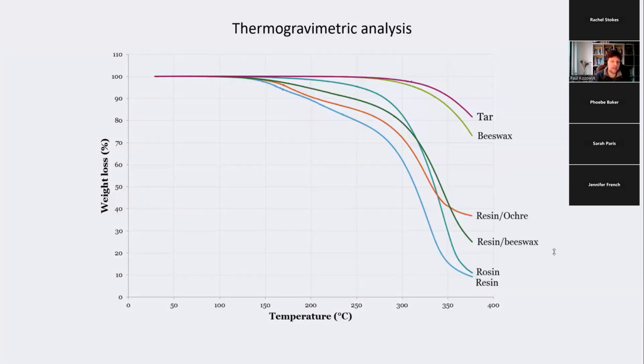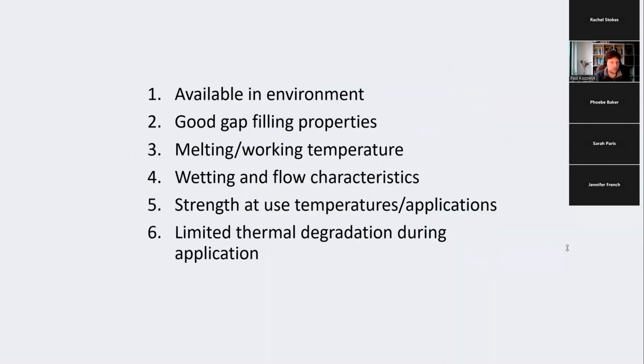With pure resin, on the other hand, after about 100 degrees, it starts to change quite significantly. This begins with the turpentine fraction evaporating, and it becomes more brittle. Then at around 150 to 200 degrees, the rosin acids start to break down and it again becomes degraded and not such a good adhesive. So you can see that the tar basically outperforms resin in most of the cases.